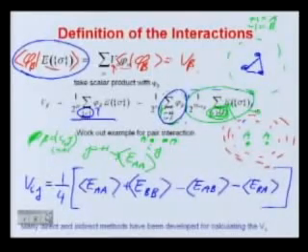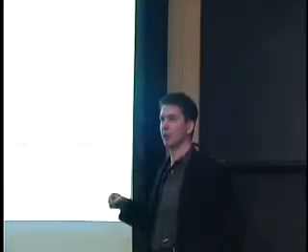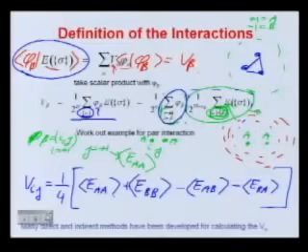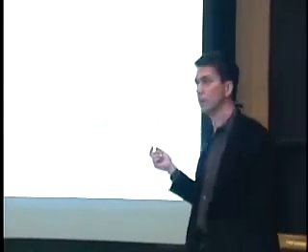But it's sort of interesting. This is the formal definition of the expansion coefficients. First of all, notice that they are not potentials. They are energies, and they are energies of configurations. So this is not the potential between the A atom at I and the A atom at J, because the configuration around it modifies that interaction substantially.